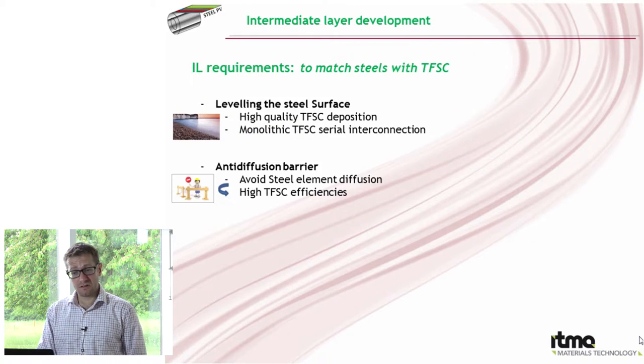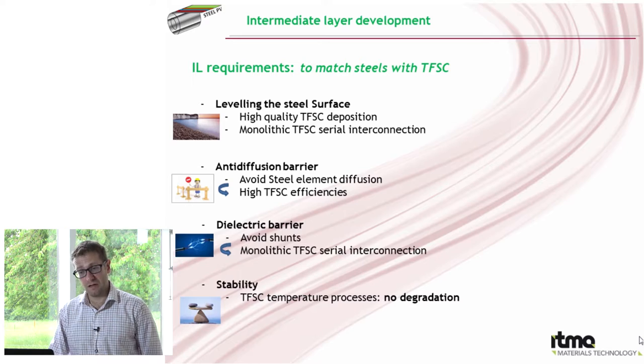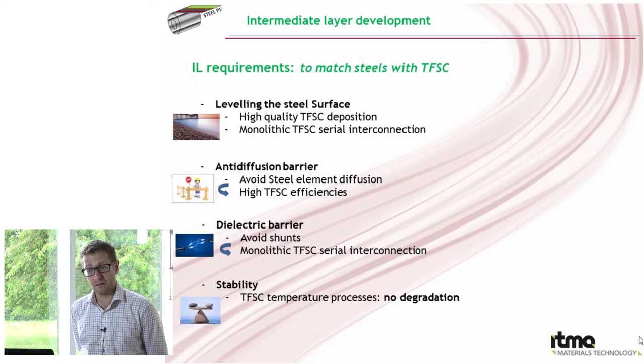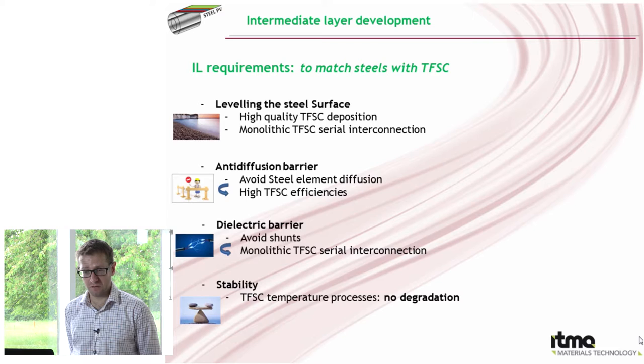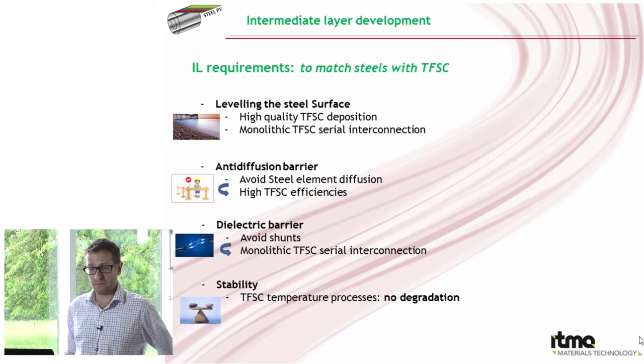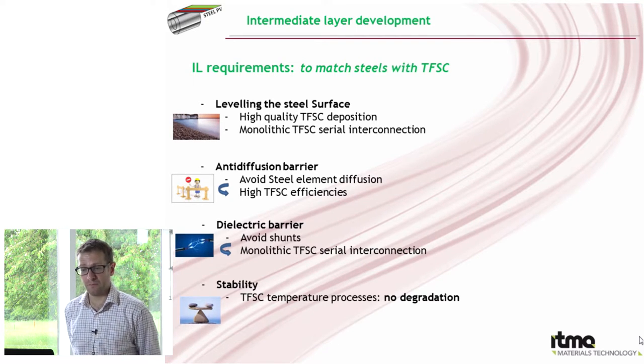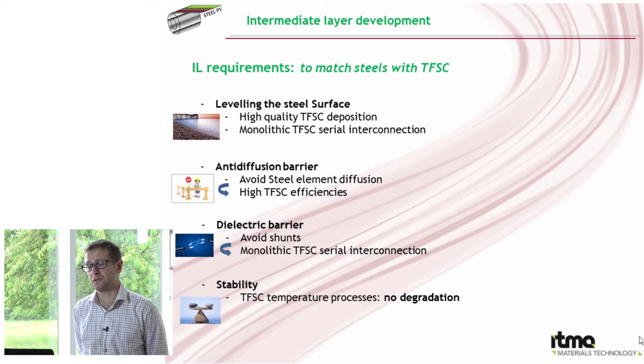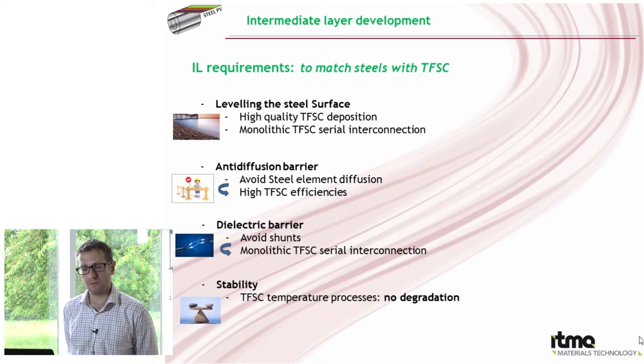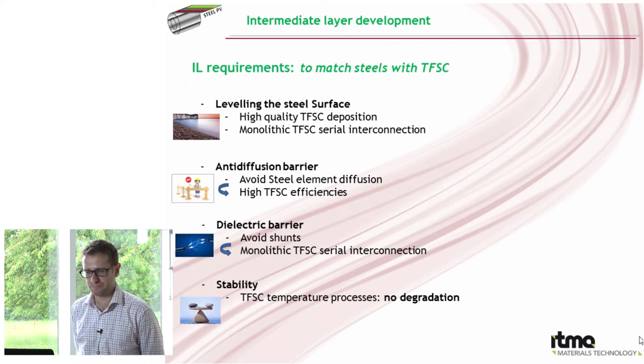However, the steel still needs to have a number of additional properties in order to make it compatible with solar cell technologies. So first of all, the quality of the steel surface isn't quite sufficiently high. So what we need to do is deposit something known as an intermediate layer. So the intermediate layer is a coating which is applied onto the top of the steel, and what it does, it reduces the surface roughness of our steel substrates, and that makes it compatible for thin film solar cell deposition and also monolithic connection in a series connected cell.